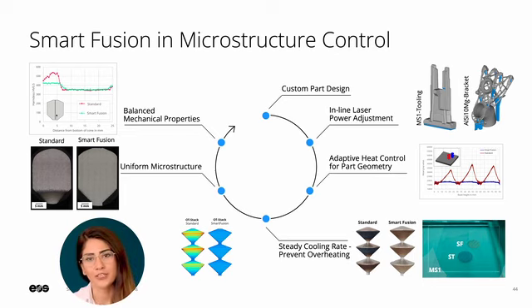When it comes to metal alloys, a consistent cooling rate is a crucial factor for achieving a uniform microstructure, as microstructural properties are coupled and linked with the mechanical properties. Having a uniform microstructure will ensure homogeneous mechanical properties. So now, with Smart Fusion, we are able to create a complex part with homogeneous mechanical properties.